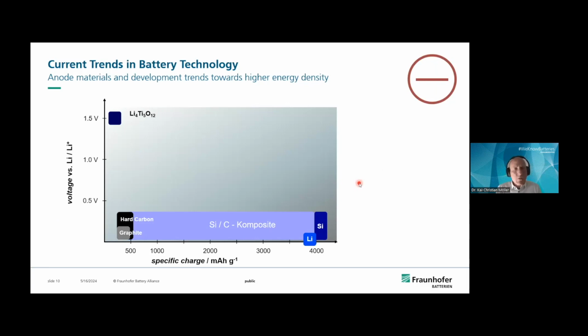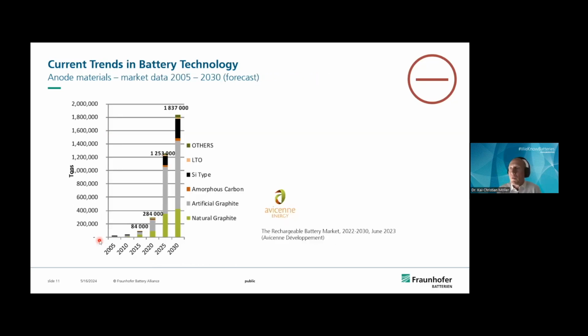The summary of the anode materials is seen here. The specific charge should be as high as possible. You find here the metallic lithium and also the silicon, which would be favored electrode materials for the future. And the voltage here should be as low as possible to give high voltages to the cathode materials. This is a market overview. Looks a little bit simple because most of the material is natural or artificial graphite, little bit amorphous carbon, and the silicon mixtures increasing in the next 10 years.